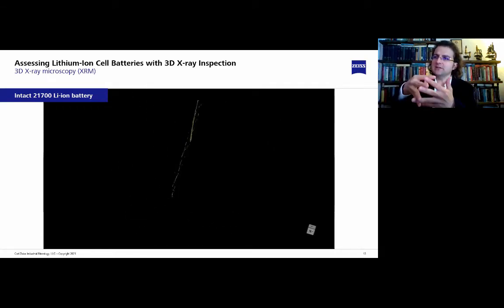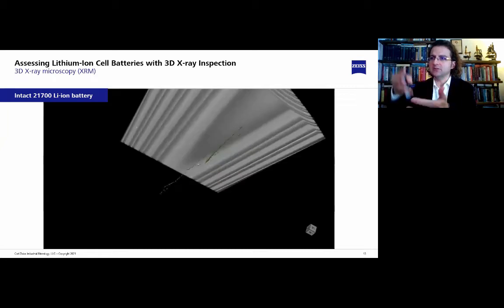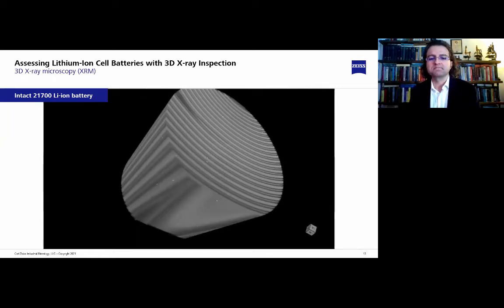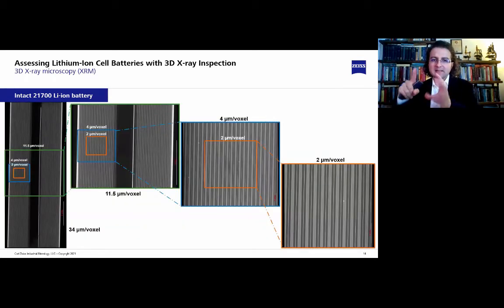By doing segmentation and putting a color in that segmentation, you can see where the crack is. In this slide, you can see how using X-ray microscopy with different sets of lenses and resolution at a distance, images of different resolution can be scanned. You see images of the whole battery with 34 micrometers voxel size, and then regions of interest scanned with 11.5 micrometers, 4 micrometers, and 2 micrometer voxel size.